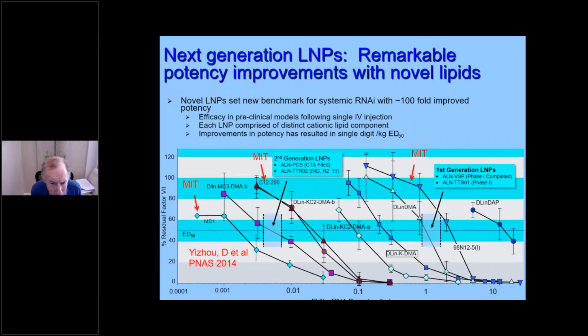It's a busy slide, but if you start out and look at the abscissa and you look at 10 mg per kg, you see the amount of knockdown you get. But over a 10-15 year period, between our work and Alnylam, we kept bringing this down probably 4 or 5 orders of magnitude. If you go down, you see you only need 0.001 mg per kg. So at any rate, we were able to show that you could make these more and more potent.